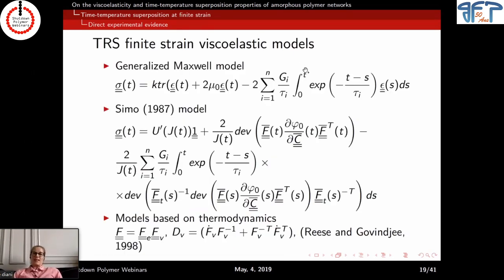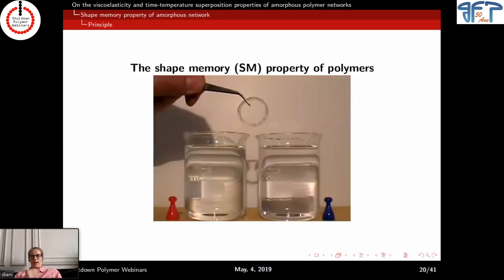Okay. So what's nice now is that I can define a simple constitutive equation at finite strain. So, visco-hyperelastic behavior. We have measured in linear viscoelasticity the shift factor for the time temperature superposition, and we have measured the viscoelasticity in terms of the relaxation times and the moduli that are associated to that. And we can transpose that directly to large deformation using either a phenomenological model or a thermodynamic model, such as the one proposed by Reese and Govindjee. So I won't go through all these equations, but it's basically writing the generalized Maxwell model in finite strain. Okay, and we're going to apply that to the shape memory property of our amorphous network.